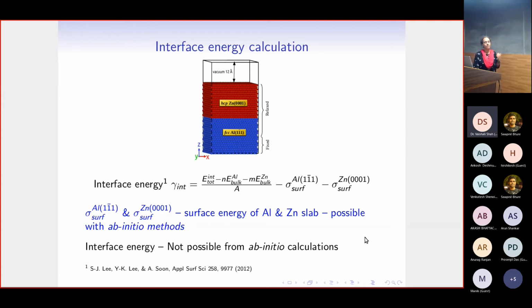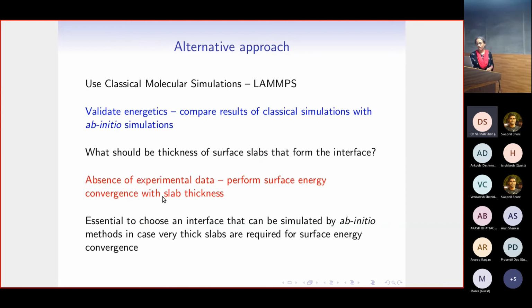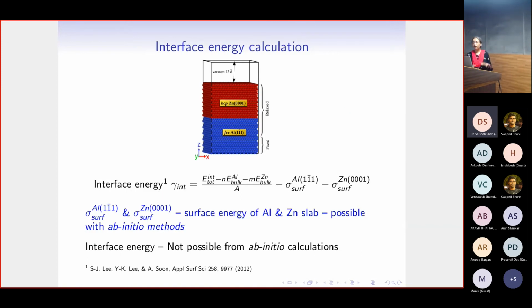Because we are interested in the solid-solid interface energy for the aluminum zinc system, we know how to get the interface energy. There is a methodology that tells us to construct the interface and obtain the energy of the interface. Once you have the energy of the interface and the energies of the individual surfaces, you simply apply this mathematical equation and you should be able to get the number you are interested in. So the surface energies for the individual surfaces we can still obtain by ab initio methods, but the interface energy we cannot obtain. So we have a methodology which we really cannot use because it's just not practical.